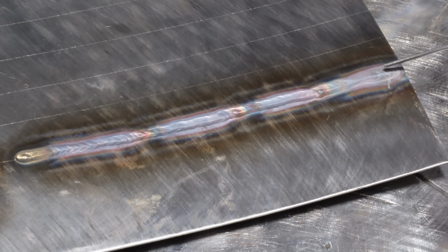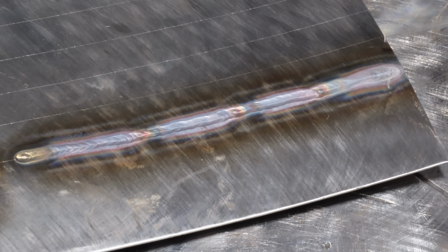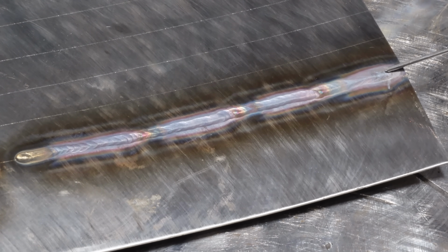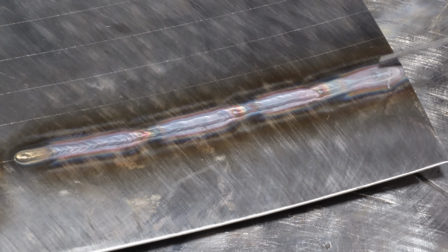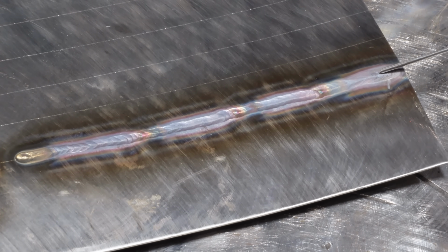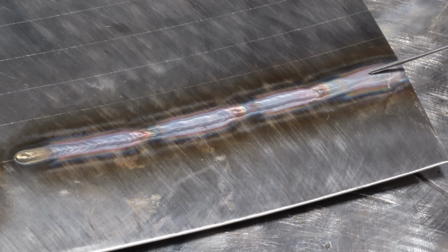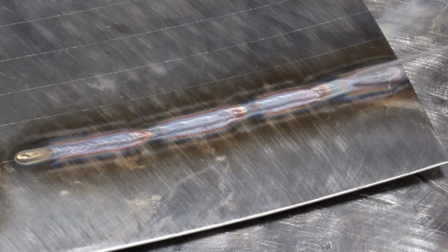You have to really use a gas lens with this stuff to get proper flow and shielding. Anyways, this was done at 50 amps, so the amperage is a bit high. The gas cup, honestly, a number 8, number 10 would have worked better. The flow was low, travel speed was a little bit too low. Everything about this is wrong.